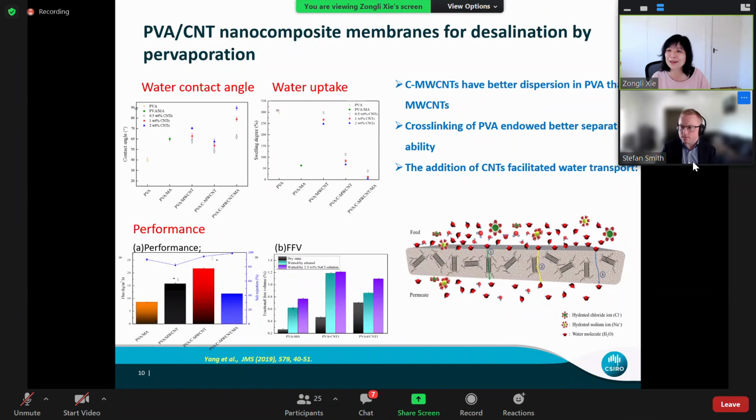We do have a lot of error trials, because some of them we thought should be good, but after we did it, we experienced delamination. So not only selecting the substrate, sometimes we also do some pre-treatment of the substrate to improve the adhesion of the two layers.